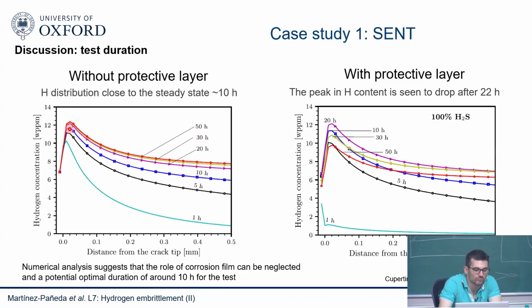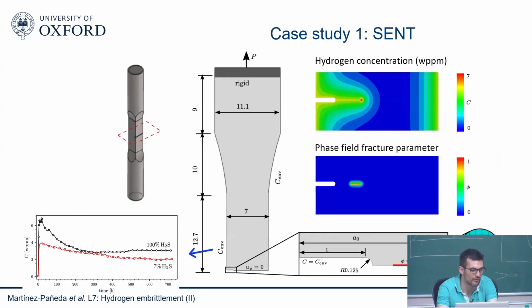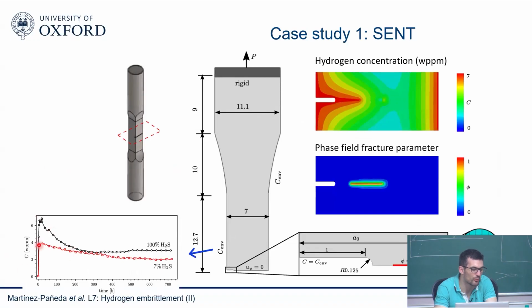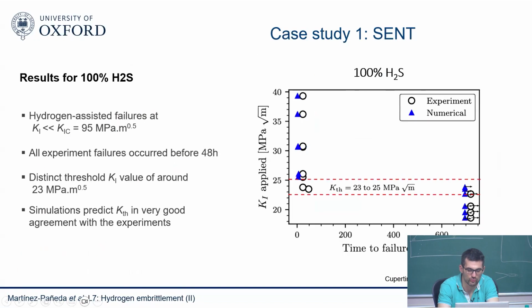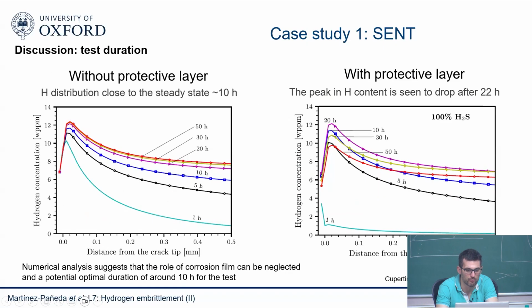So maybe 10 hours is all that you need to run your experiment, and not 700. But there's an effect of this protective layer. Remember, at some point you generate this oxide. And so this is a case where we just basically simulate hydrogen transport, imposing a constant hydrogen concentration. But we know that the hydrogen concentration is not constant. The hydrogen concentration goes down with time. So we decided to simulate how the hydrogen concentration goes down in time.